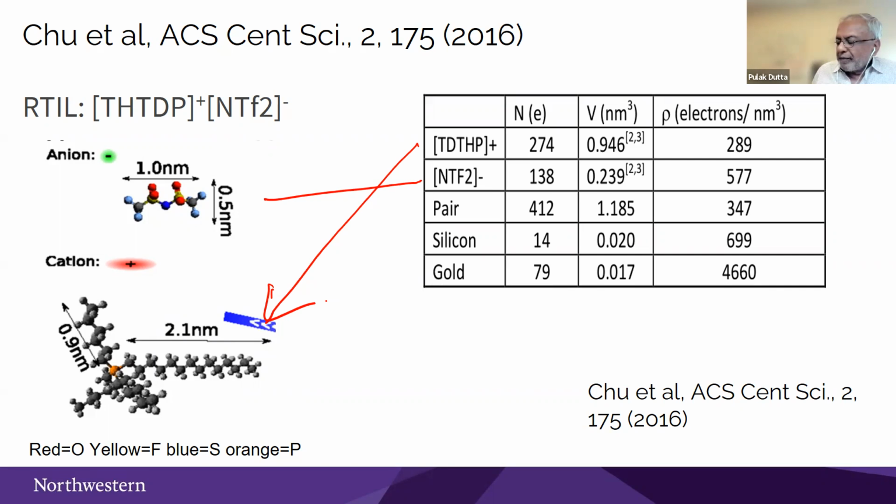But there's a problem. The problem is that the electron density of gold is awfully high. The result is any order next to a gold surface is just very hard to see. Contrast due to layering or anything like that just doesn't show up against the strong density of gold.